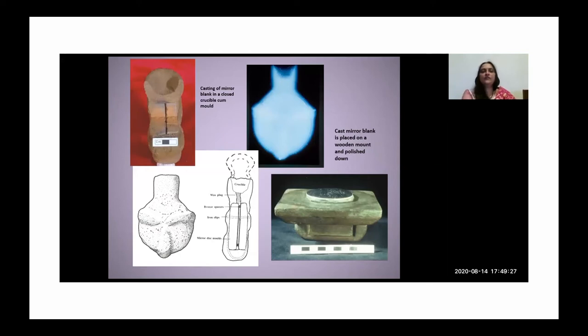Yeah, so to explain what the cross-section of that closed crucible cum mold looks like. So you see here, there are these two discs and this gap between these discs and the cup on the top. So that is where the alloy to be cast is kept. And of course, this is just a section to show you that. And down below, you're just looking at the sketches. And on the side, because another of the techniques which is useful for looking at artifacts is X-ray radiography, that's a radiograph of the crucible. So you can see in the outline the disc molds that I was talking about, and the top is a cup. And after the metal has been put there for casting, the whole thing is sealed, and then it is tipped over and so on.